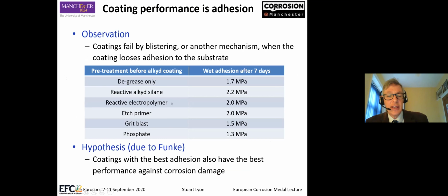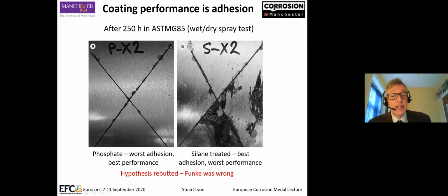So we did this work where we took a number of different treatments of steel: degreasing, etch priming, grit blasting, phosphating, a reactive electropolymer, and a reactive alkyd silane. These are materials where we have functional groups added which are designed to chemically link into the backbone of the polymer. So the reactive alkyd silane had by far the best wet adhesion after 7 days, and the phosphate had the worst wet adhesion after 7 days. And yet the phosphate gave by far the best performance, and the silane treatment by far the worst performance.